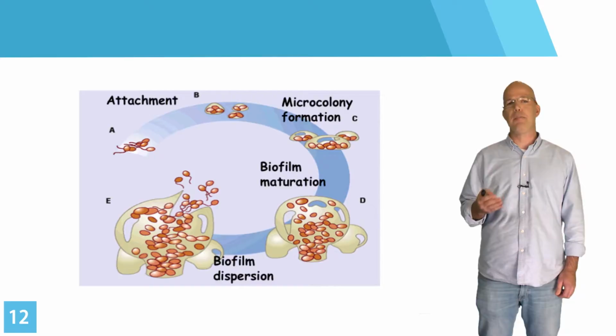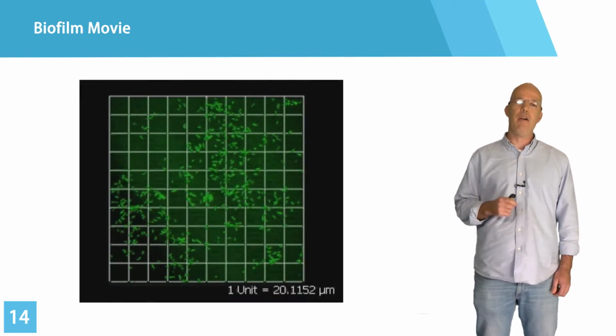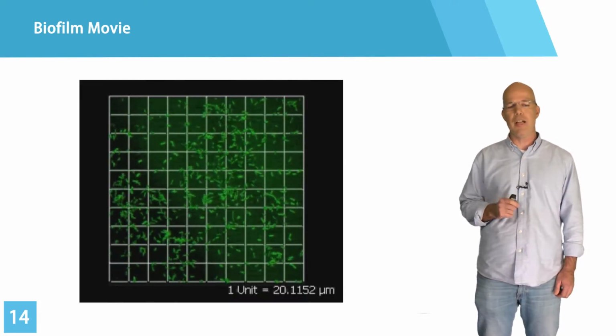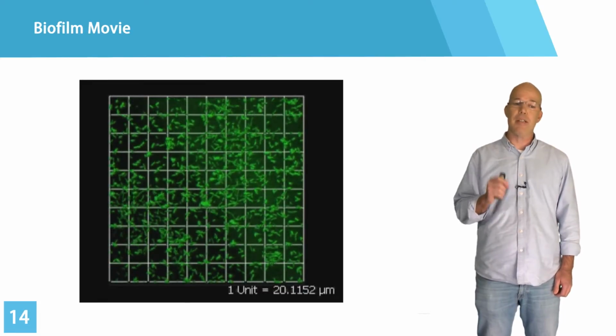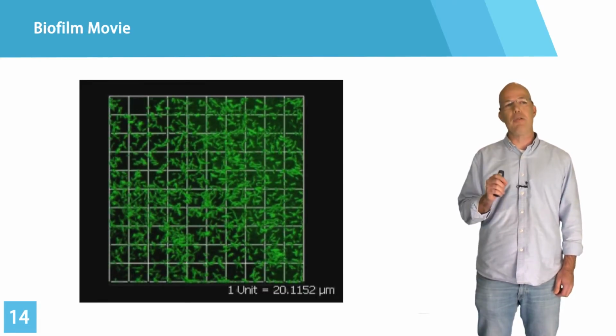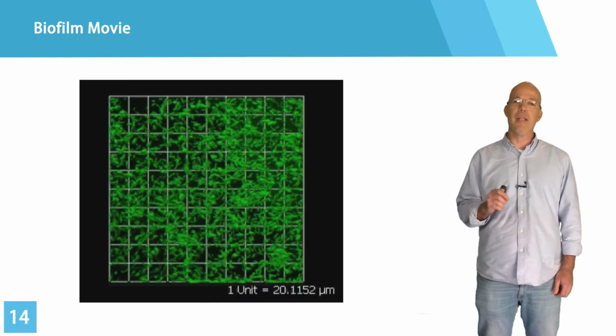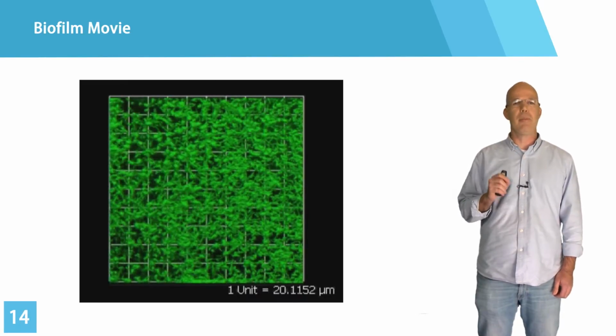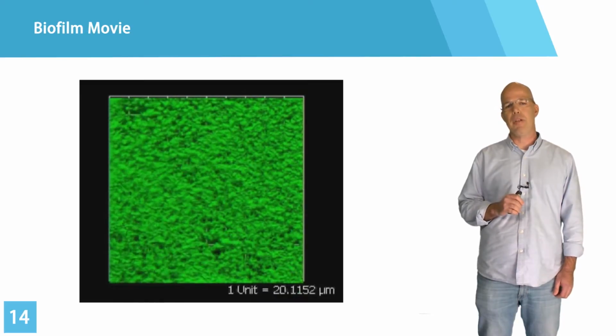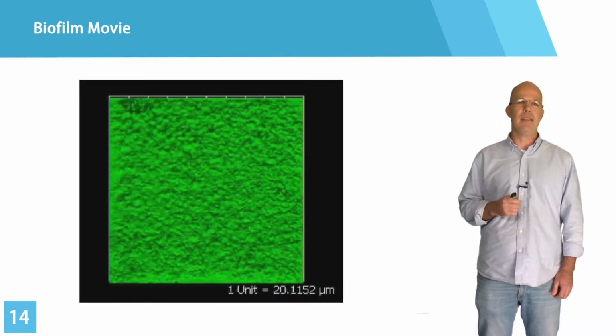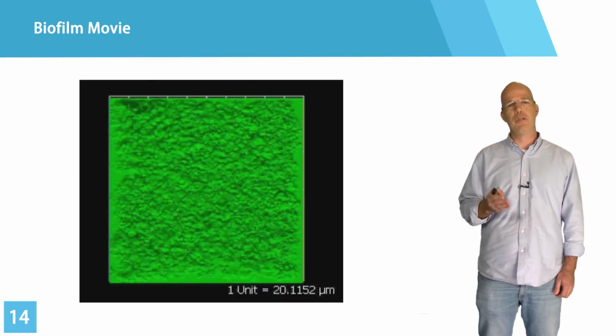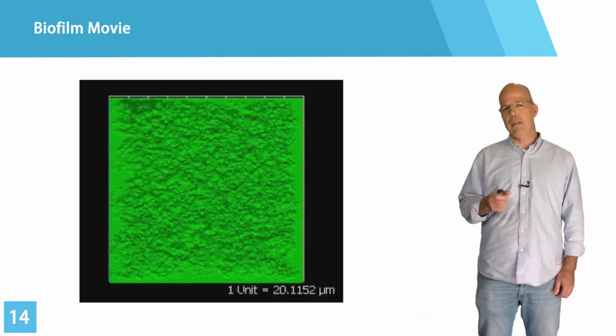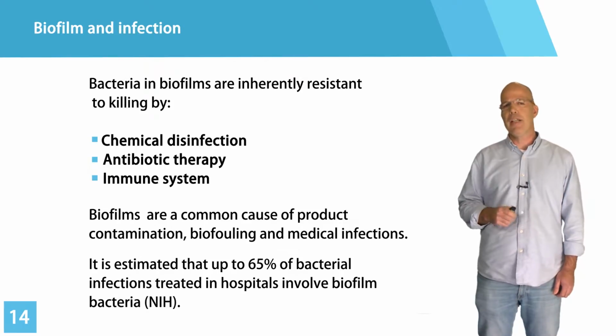And this biofilm can disperse free-living bacteria that can inoculate new niches. The next movie shows you a biofilm formed in 24 hours. The green dots moving on the surface are actually bacteria, and you can see some of them running on the surface. After a few minutes, and we can actually track that, we see that the bacteria slow down and make a biofilm. If you can imagine something like this happening on your heart or on your joints, that's a problem. The main issue about biofilm formation is that once biofilms are formed, they are highly resistant.